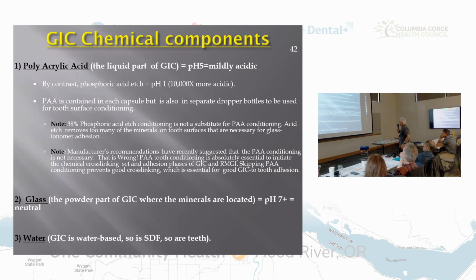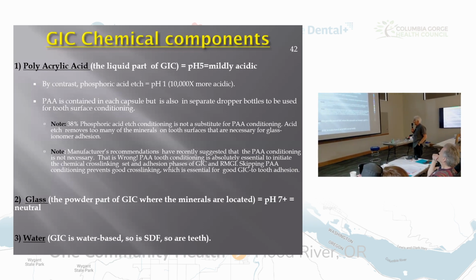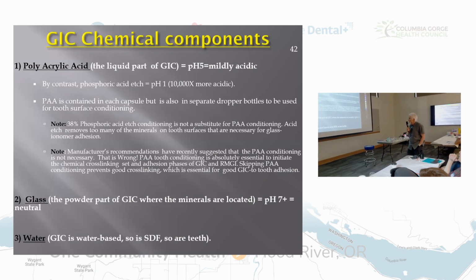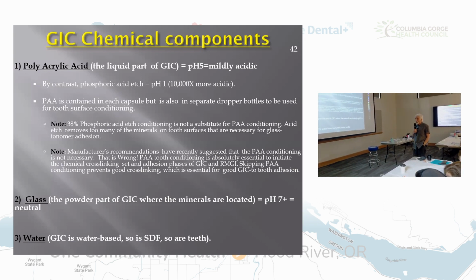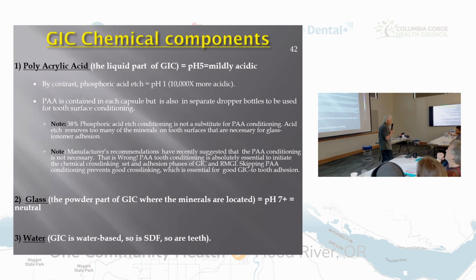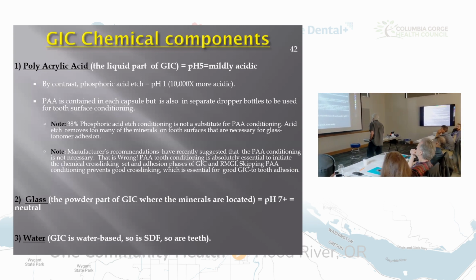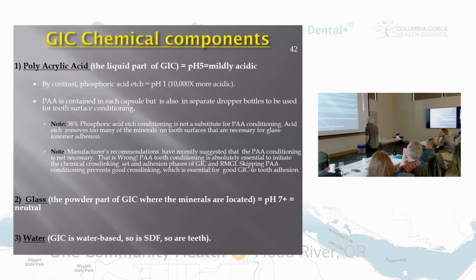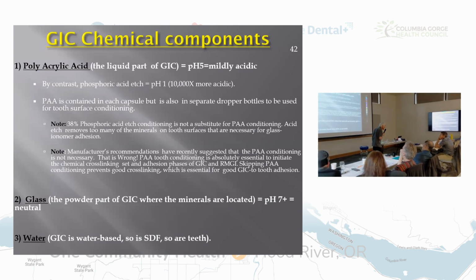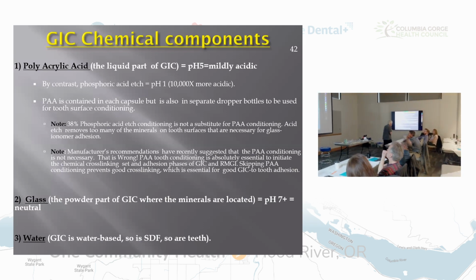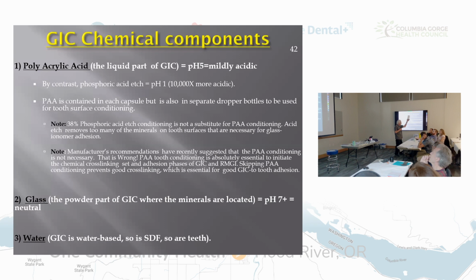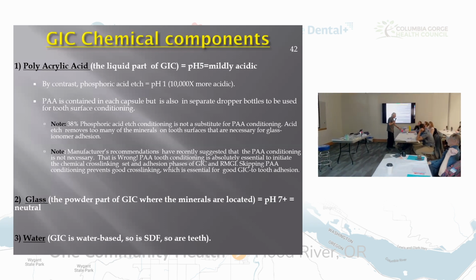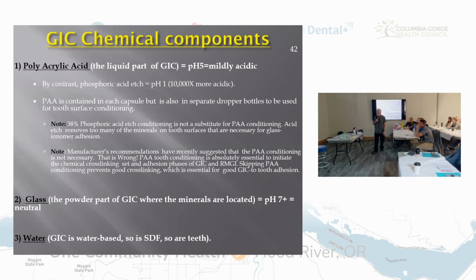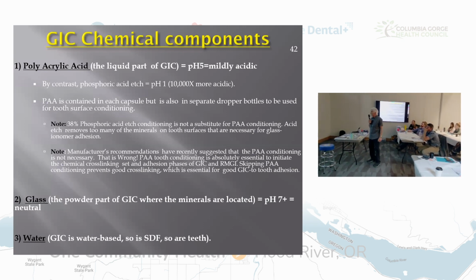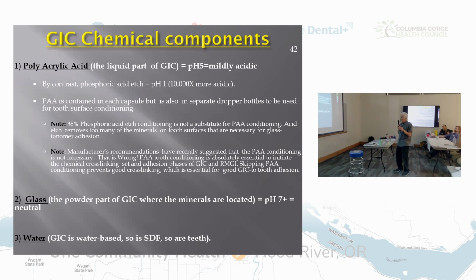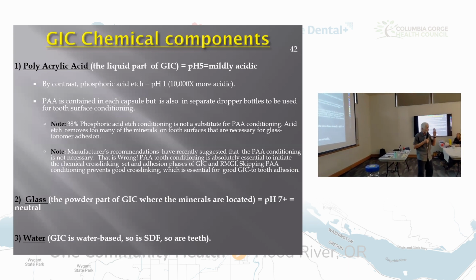It is not a good substitute. Acid etch removes too many of the minerals on the tooth surfaces that are necessary for the glass ionomer to adhere. Okay? This is really important. Doug and I are disgusted about this. But manufacturers have recently started suggesting that the polyacid conditioner isn't necessary. That the polyacrylic acid is in the capsule. And the manufacturer's saying, well, you don't need to put more on the tooth. And we're saying, no, you're wrong. You do. Okay? Polyacrylic acid conditioning is absolutely essential to initiate the chemical cross-linking set, which is the second set.